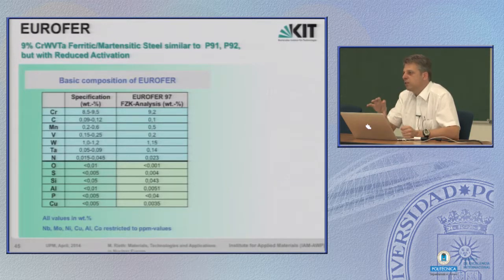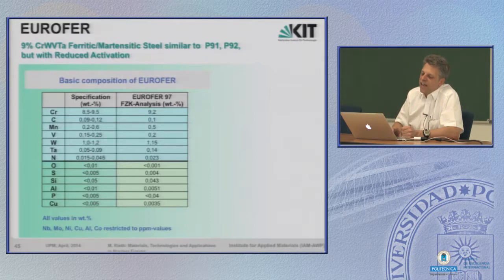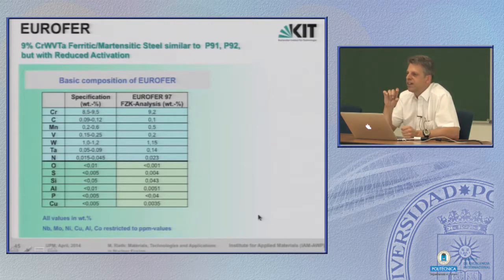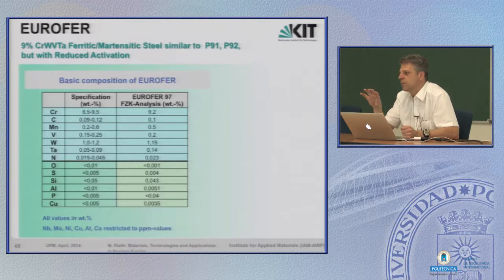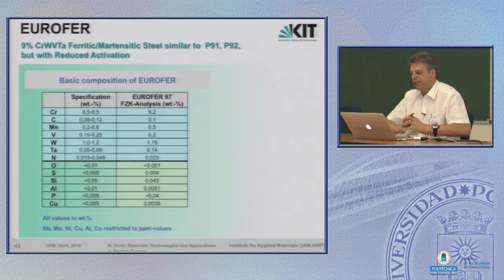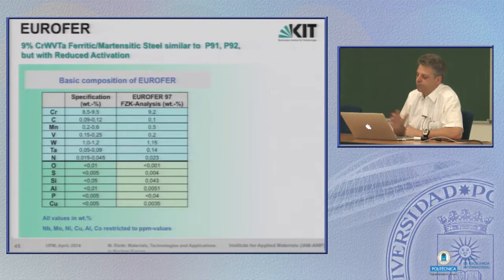For example, if you shut down the reactor and you want to exchange a breeding blanket or a divertor cassette, then especially elements like cobalt and, to some amount, tantalum keep the activity rather high, but only for a few weeks. So in the long term, when it comes to waste, that's not a problem, but you want to exchange your components rather quickly. Two weeks shutdown for a reactor is already a significant long time. So if you have these elements inside, this has an effect on the interchange of breeding elements or things like that.